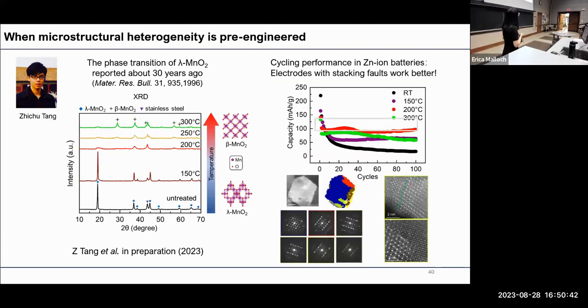For the best performance here, the particles were preheated at 200 degrees C. If we use 4D STEM to look at these particles, this is a particle with a lot of defects, as shown here. You can see the electron diffraction patterns now become very stretched. We still have ongoing studies on this project, but the immediate scientific message is that electrodes with stacking faults actually work better than single crystalline electrodes. This is an amazing example where heterogeneity can win over order in material performance.